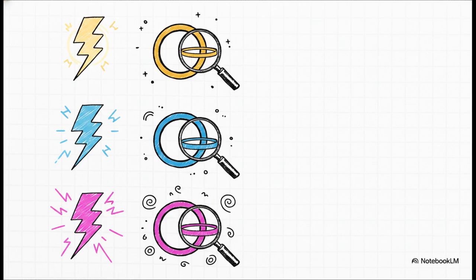Notice how at just 15 volts, the layer is about 30 nanometers thick, giving us a nice gold. Crank it to 70 volts, it grows to 90 nanometers, and boom, we see blue. Push it all the way to 110 volts, and the layer hits 140 nanometers, creating this incredibly vibrant magenta.